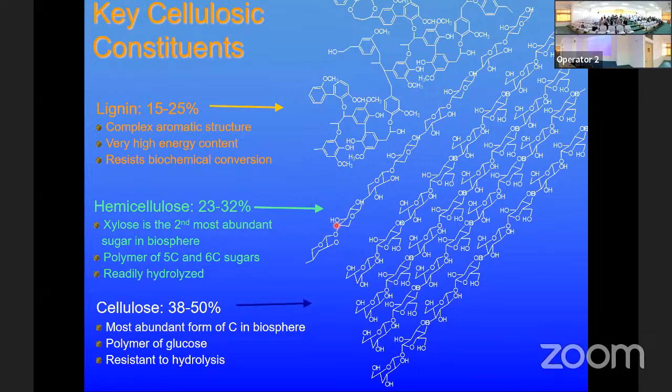My question to all of you is, what is the reason for this rigid structure? Because there is a lot of lignin here. There is a lot of lignin that makes a tight connection with the cellulose and the hemicellulose. Yeah, that's a good answer. So wood has a rigid structure, but paper came from cellulose only, with no lignin, or a quite low concentration of lignin, so it is a very soft material.